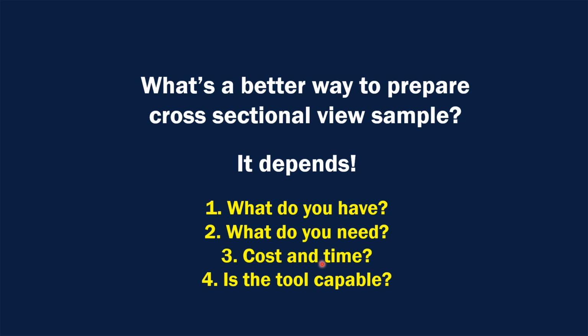Again, edge cleaving is quick and easy. It does not cost you anything, and it may give you the information you need. On the other hand, it takes about 1 to 1.5 hours to FIB a sample, with added cost, but it can give you more details about your samples. Last, you also need to consider the tool limitation.